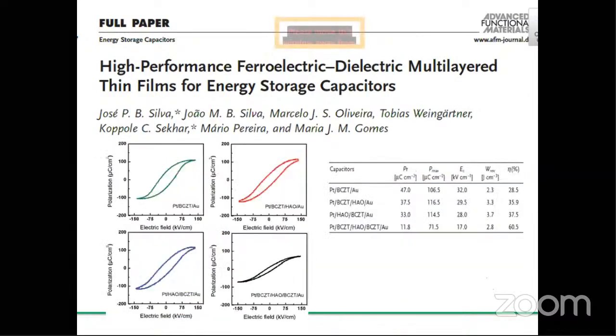If you look at these ferroelectric properties, you can observe that they are highly influenced by the ferroelectric-dielectric multilayer. The first green hysteresis loop is only BCZT. I have not used any dielectric layer or multilayered film. We have not used anything. In the next cases, when we used HAO at different positions, these hysteresis properties are modified. From here we can understand that I can improve the relaxor behavior. You can see they become more slanted and slim when we introduced the HAO. Like that, we can tune the relaxor behavior of BCZT by using dielectric materials.